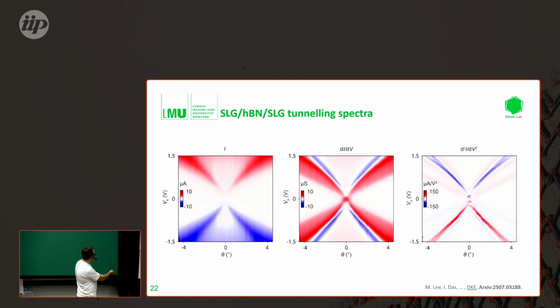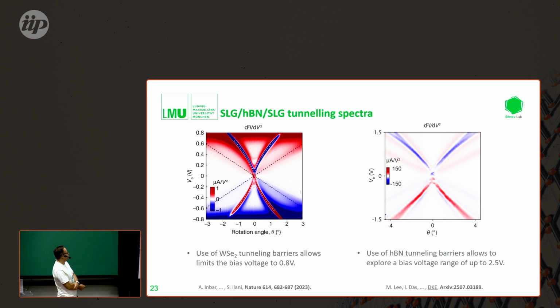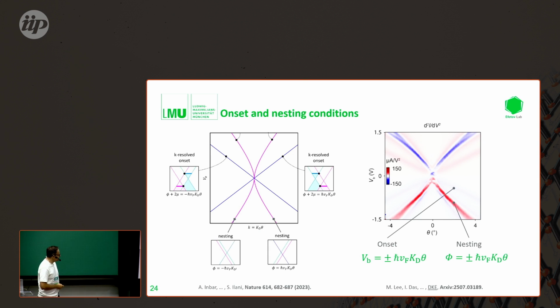And if you are familiar with the band structure of graphene, you can already guess that there is some spectral information here that resembles a Dirac cone. One can start analyzing the spectra in a little more detail, and this has been done by Shahal already in his first paper. The two features that one sees quite clearly in the second derivative, a little faint here, are two types of lines: this X-shaped line, and this hourglass-shaped line, and those two lines are explained in the following way.